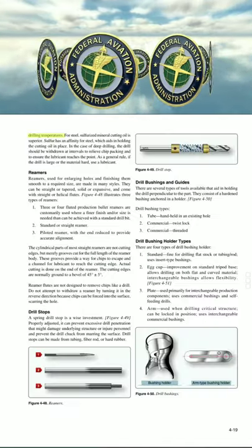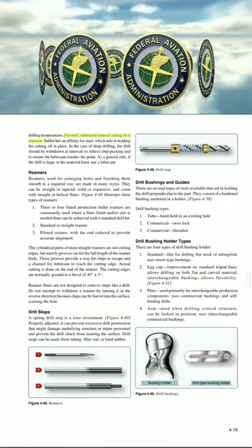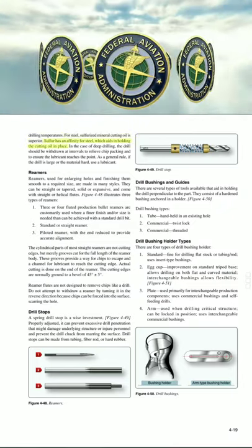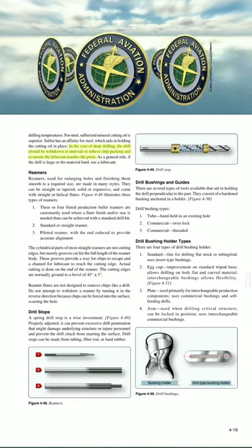4-18. Drilling temperatures. For steel, sulfurized mineral cutting oil is superior. Sulfur has an affinity for steel, which aids in holding the cutting oil in place. In the case of deep drilling, the drill should be withdrawn at intervals to relieve chip packing and to ensure the lubricant reaches the point. As a general rule, if the drill is large or the material hard, use a lubricant.